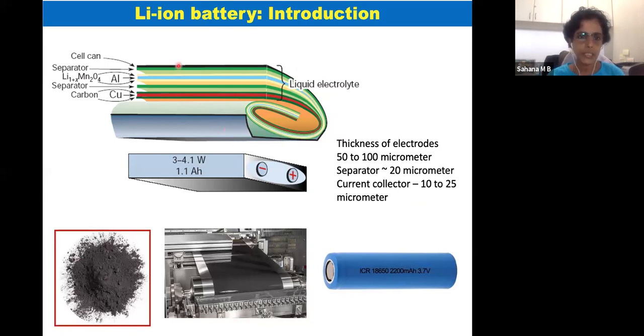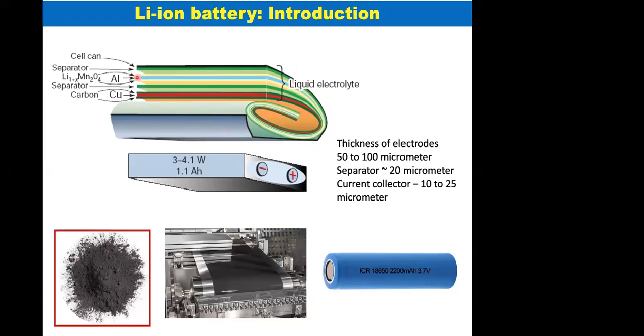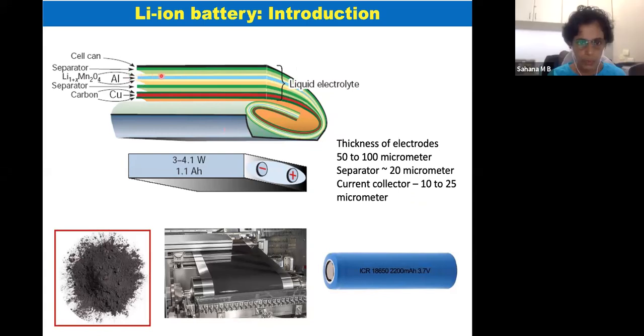And now if you see the layers here, the color here, the blue line here, that corresponds to a current collector, which is aluminum, which is metallic, and the electronic conductivity is very high. And the copper, which is a current collector for the anode, again, the conductivity is very good. The yellow lines here correspond to the cathode coatings.